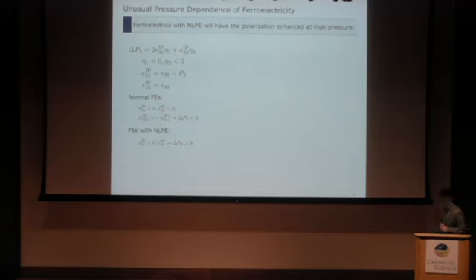Okay. So a natural consequence of negative piezoelectric response is the pressure-enhanced ferroelectricity. So this gives a very general explanation. So delta P3 is the pressure-induced polarization change. Because now we need to consider the effect from volume change, so we need to use this improper piezoelectric coefficient. So the strain change is negative.